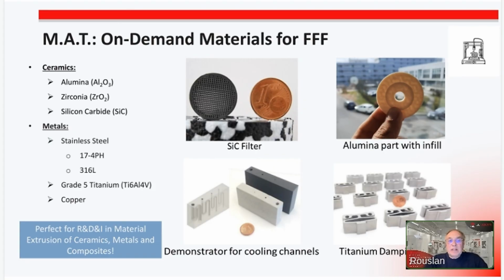We can print stainless steel, as I said, different grades, grade 5 titanium, copper, and also even polymers up to the temperature of the maximum nozzle temperature on this machine, which is 250 degrees. So you cannot print some high temperature polymers, but you can print the most common ones.